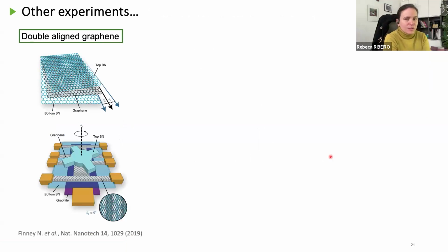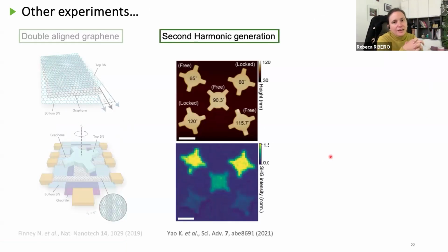Well, other groups since then have also used this technique for different purposes, for example, to make double aligned devices, which means that they align the top and the bottom layer, and they can see the effects of symmetry breaking and symmetry restitution, which are also observed in second harmonic generation. So these are optical measurements. Here we have different handles at different orientations. So we are either going to restore the inversion symmetry of the system, and that's where we don't see any response, like here, for example, there is no second harmonic generation, or we are going to break completely the inversion symmetry on the interface, and that's where you have a strong second harmonic signal.